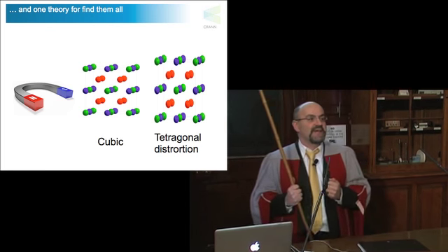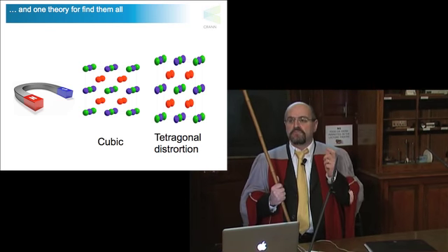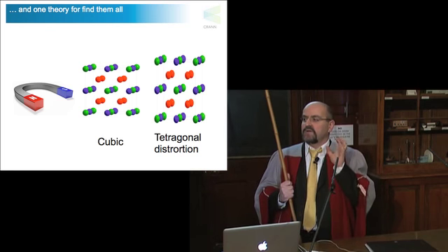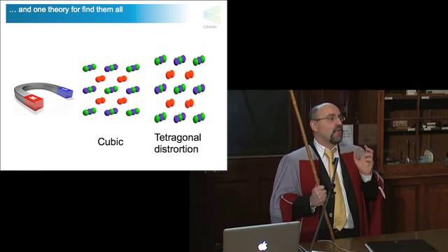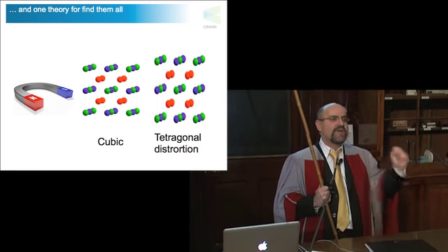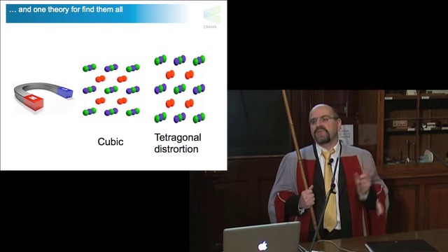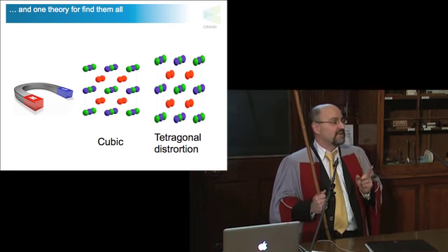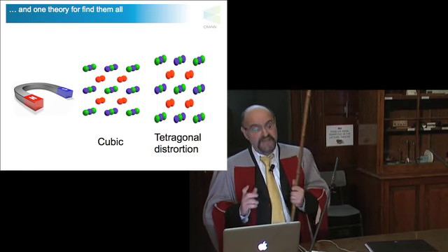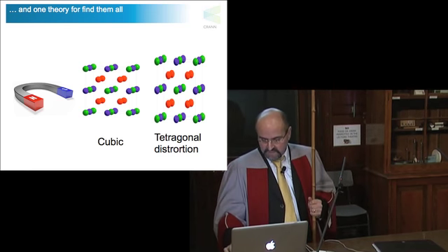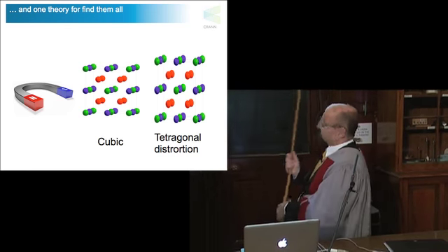So the argument is, okay, we found a rule, some sort of intuitive rule, by which we can calculate the anisotropy. Now, why do we do that? We don't just go ahead and calculate the anisotropy, because this is a very painful calculation to do, very heavy, so we don't want to do this right away. And it must be very accurate, so it's very easy to get it wrong. But this rule is quite simple.